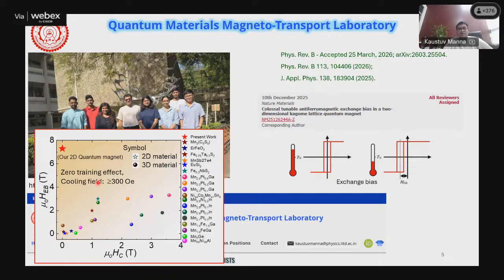But in our compound, which we have discovered in IIT Delhi, this is a 2D material. For the first time, we have shown that there is no training effect at all. It doesn't matter how many times you switch the magnetic field. If you have 1 Tesla exchange bias, it stays locked at 1 Tesla. Even the cooling field is only 300 Oersted, very low, but you can get exchange bias beyond 7 Tesla. 300 Oersted is nothing, because a toy magnet that kids play with can be up to 1000 Oersted. So we have got the ideal magnet that one can dream of.